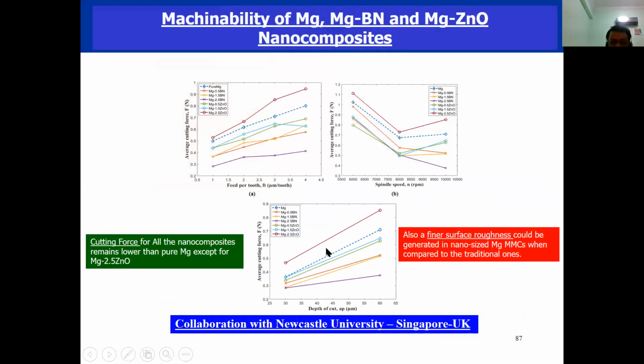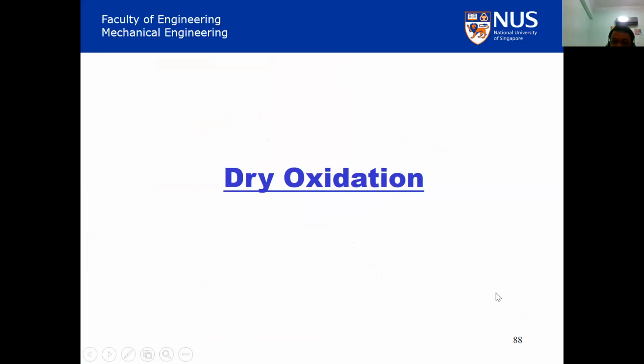We also did some machining work with Newcastle University, both in Singapore and UK. We gave them a number of nanocomposites based on magnesium, and they say the cutting force for all the nanocomposites is lower except for only one material, and they are able to get a good surface roughness as well. So you can make the machining faster.